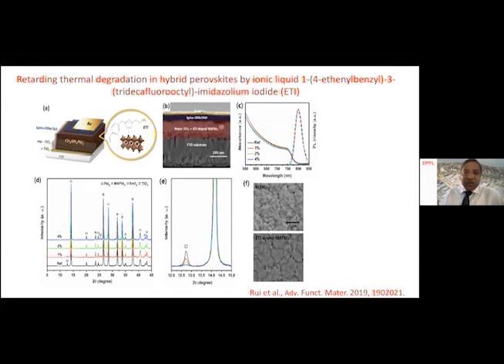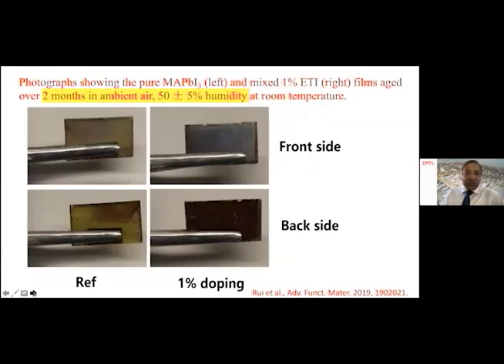So the cell configuration is shown here. Again, it's a NIP configuration, and the absorption spectral properties don't change significantly by adding 1%, 2%, or 4% ionic liquid. The surface image is shown here with the ETI. This is the nickname of this ionic liquid, and this is without any ionic liquid. Now, the question is, what is this ionic liquid doing? See on the left side, without any ionic liquid, this is under air, 2 months, ambient air, 50% humidity, the perovskite color has gone in the reference sample. And if we put 1% of this ionic liquid doping, see from the front side and the back side, the color is almost intact compared to the reference sample. This is one advantage.